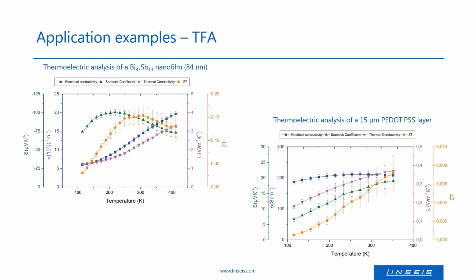and here one can see that the measurement was performed in a temperature range of 120 to 400 Kelvin, and this thin film was prepared by thermal evaporation. And one can see here that in one run, one could get the thermal conductivity in purple, the electrical conductivity in blue, as well as the Seebeck coefficient. And based on that, then the figure of merit here in orange was calculated, and the material is fully analyzed here with the TFA.